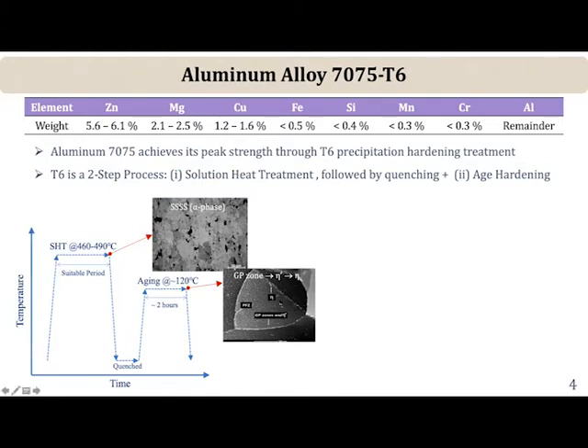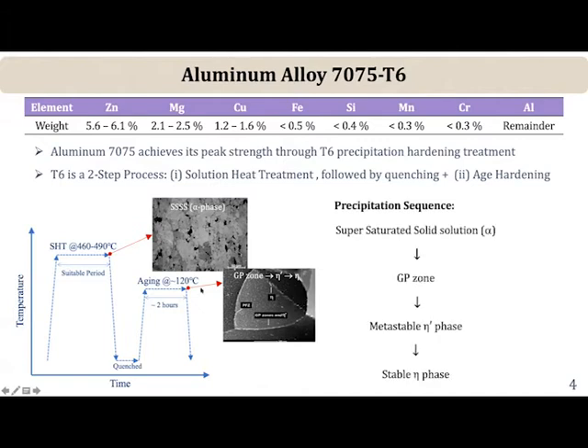The precipitation proceeds in steps. It involves initially a supersaturated solid solution. You get GP zones, which are almost pure zinc. That's followed by formation of eta prime, which is a metastable precipitate, and then the equilibrium stable eta phase, right? And the eta prime is the primary strengthening precipitate.